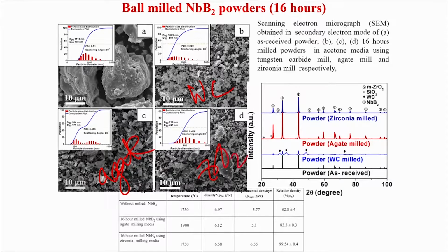Only in the case of zirconia do you see that D90 is 713 nanometer and D50 is 491 nanometer. In agate, the D50 value is apparently fairly low, that is 171 nanometer, but there is a lot of contamination from agate, as you will see later. Now, if you see the X-ray diffraction patterns, the contamination from silica is quite extensive in the agate case, and with tungsten carbide milling media there are also small amounts of tungsten carbide present, and niobium boride is quite significant in all these cases.